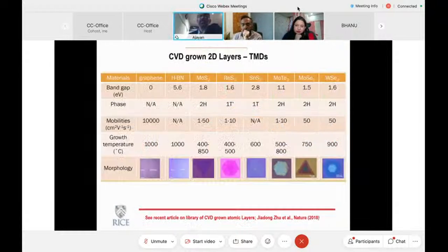Another system that has gotten a lot of popularity is the semiconducting transition metal dichalcogenides like molybdenum sulfide and molybdenum selenide. And I think about 75% of the work in 2D materials in the last 5 to 10 years has been on these TMD systems, because they show good semiconducting properties. Graphene is a great material, but it is still kind of metallic. It doesn't have a band gap. So one had to look for semiconductors, and these are traditional semiconducting materials.